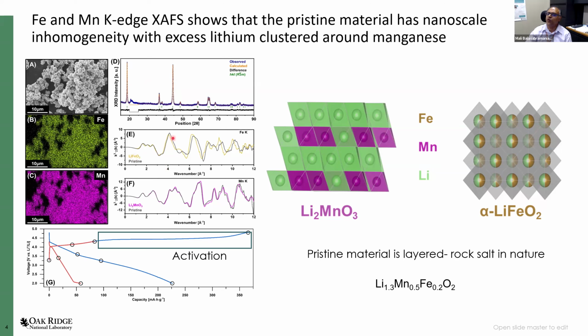the iron XAFS is very similar to one of the end members, LiFeO2, which is a cubic material, while the manganese XAFS is more similar to that of the parent material Li2MnO3. So this shows that on this length scale that XAFS is sensitive to, on a nanoscale region, these materials show nanoscale inhomogeneity with the excess lithium clustered around the manganese, just as the excess lithiums are present around the manganese in this layer as shown here. And the fact that the XAFS of iron is largely similar to LiFeO2 also shows that we have something which looks more like a cubic LiFeO2-like structure around the iron in this material.